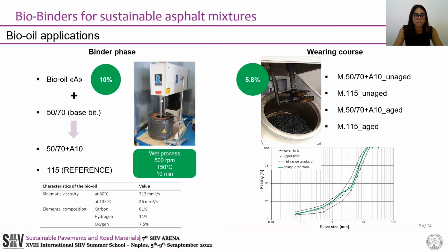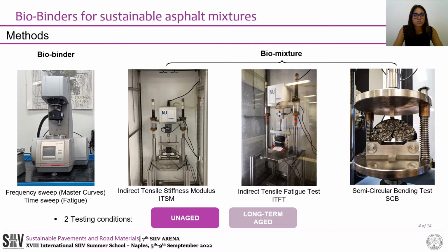as reference material. The same binders were also used for the production of asphalt mixture for wearing course, characterized by the same design gradation and binder content equal to 5.8%. Thus, rheological tests, frequency and time sweep, were run in order to obtain master curves and to compare the fatigue response of both binders.